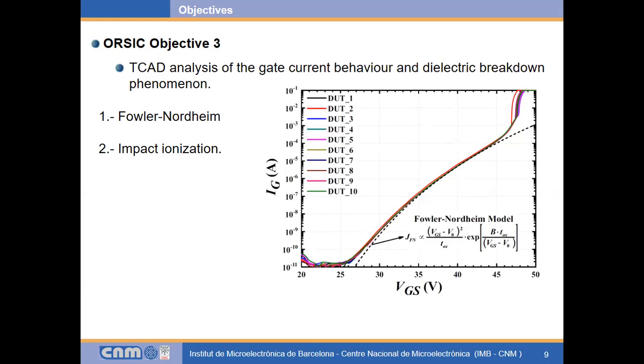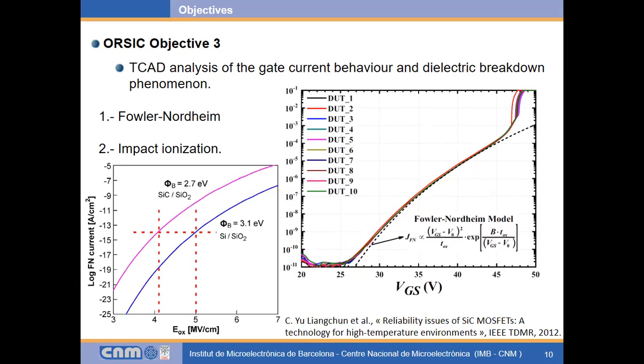This is the third objective, which is to reproduce by means of TCAD simulations the current behavior. We will take into account the Fowler-Nordheim phenomena and the impact ionization. Fowler-Nordheim is important, especially in SiC, in such tests, because of the lower barrier height, as well as the fact that the oxide is submitted to higher electric field, because its thickness is lower than in silicon devices.